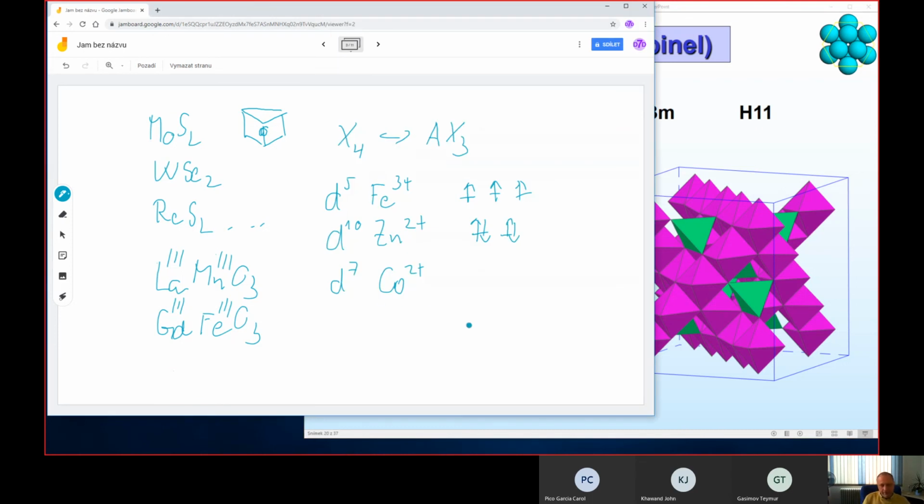One is the normal spinel, like MgAl2O4, but even this spinel, which is a mineral, when you find it in nature, sometimes the magnesium and aluminium are partly interchanged, so they form a solid solution or substitutional defects.